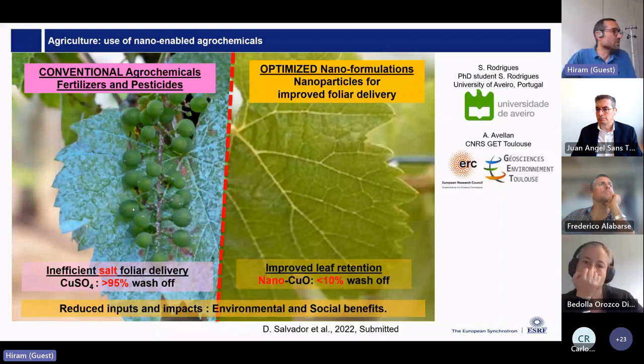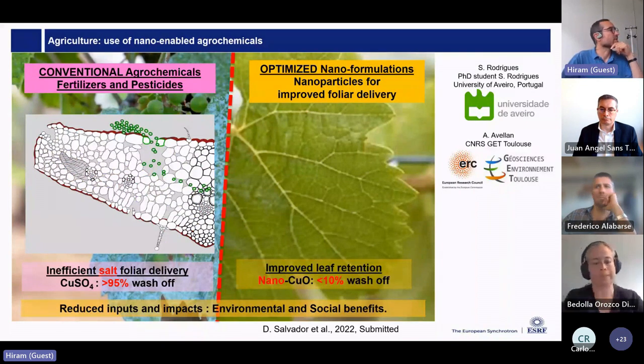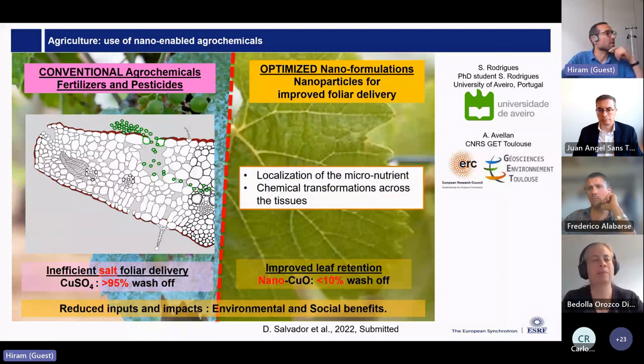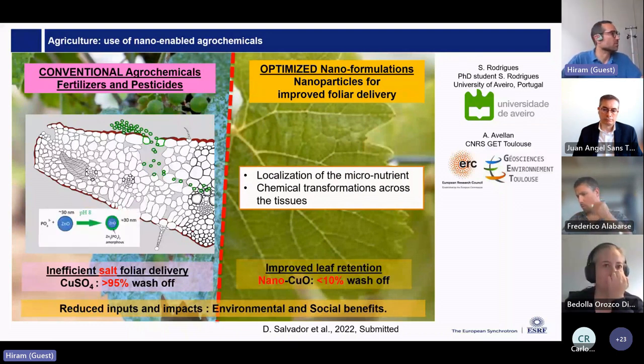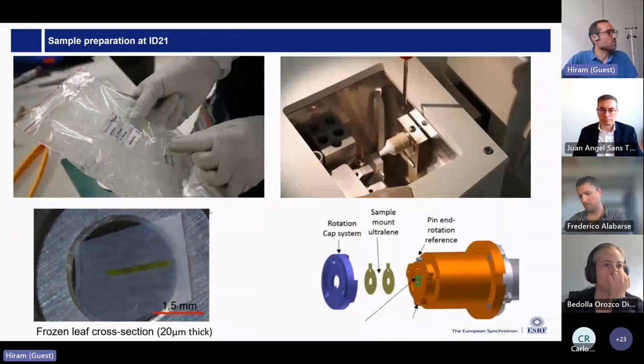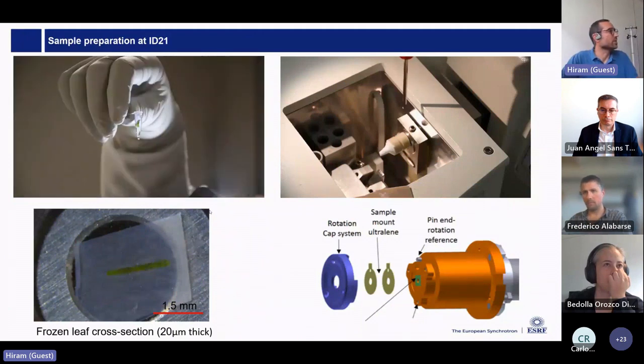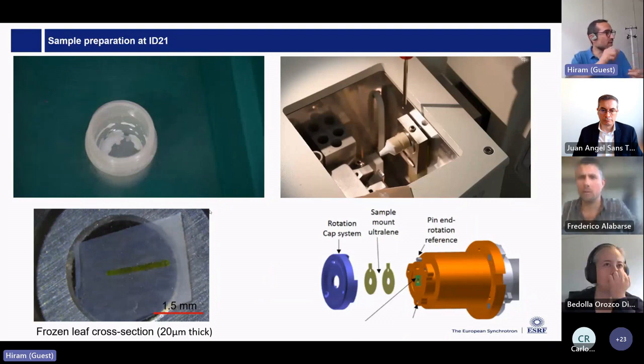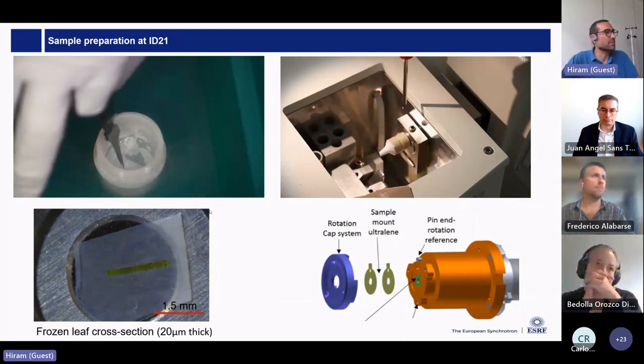So the nanoformulation is quite an interesting option, but we have to investigate exactly if the benefits are there, and if there are no risks that we are not observing. So we want to know, once we deposit the particles on top of the leaf, how they travel across the different tissues, and for that XRF and X-ray absorption spectroscopy can give you a lot about their localization and the chemical transformations. So I will show you a bit of the results with zinc oxide, which is a nutrient. And just to quickly summarize what we do for preparation: portions of the leaf are introduced into this OCT, and they are cryofixed at the beamline.